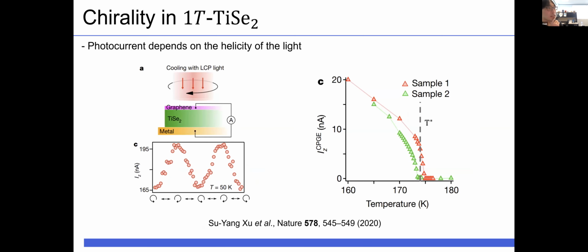So let me introduce another experiment. Su Yang and collaborators first measured macroscopic chirality in 1T titanium diselenide. They measured photocurrent depending on the polarization of the light. It's very interesting. In their research, they shine circularly polarized light while cooling the sample. For example, let's say that they shine left circular polarization. When the sample is cooled with left circular polarization, the photocurrent is also maximized at left circular polarization and minimized at right circular polarization. The right figure shows the difference between the maximum and the minimum. And there seems to be a phase transition at about 175 Kelvin, which is 25 Kelvin below the CDW critical temperature. So therefore, they claim that there is one more phase transition at T star, and it breaks the chirality.